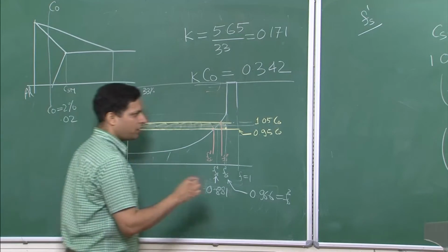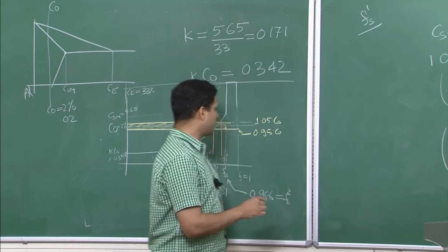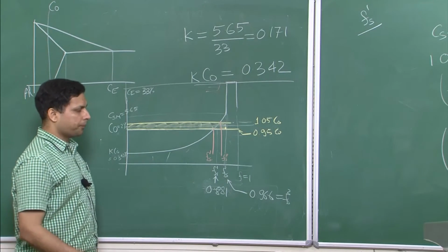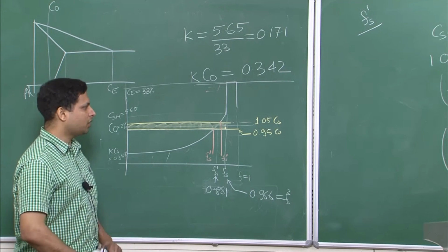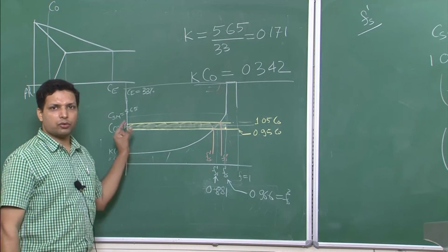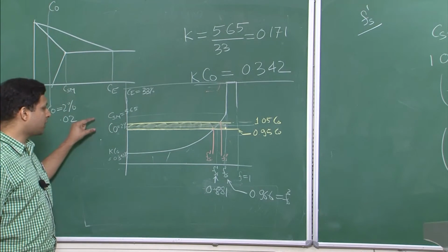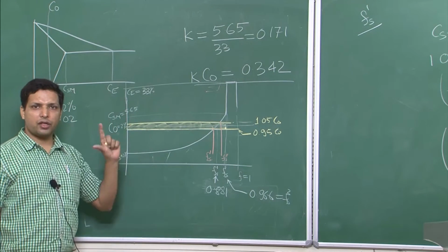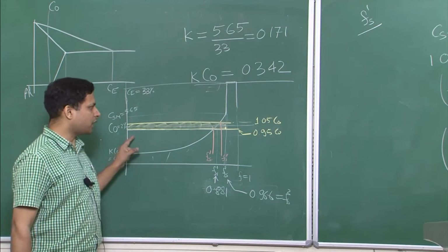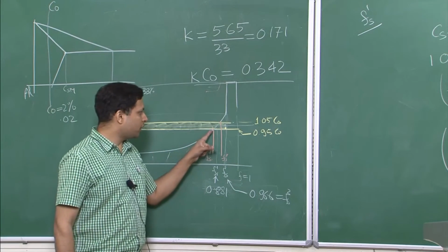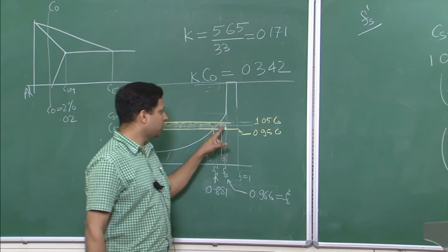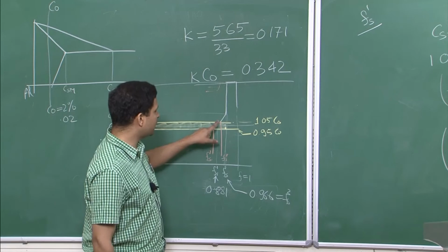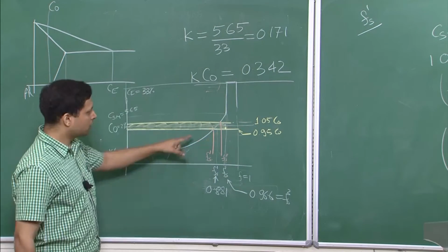So, you see it is a very small fraction that lies within this C naught value. This is a very interesting piece of information: although the overall composition is C naught, the composition which lies within this plus minus 5% of the overall composition is a very small fraction. Most of it lies outside, and in fact most of it lies below it, and beyond this Fs, the value that we found over here, 0.966, you see values higher than CSM.